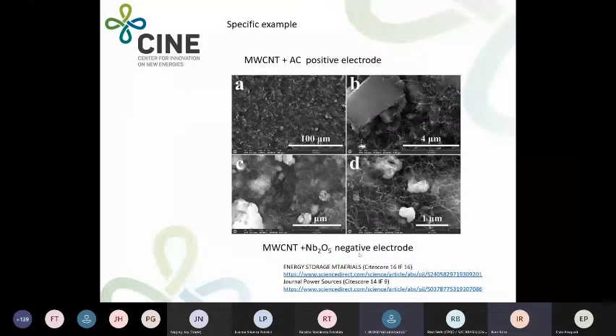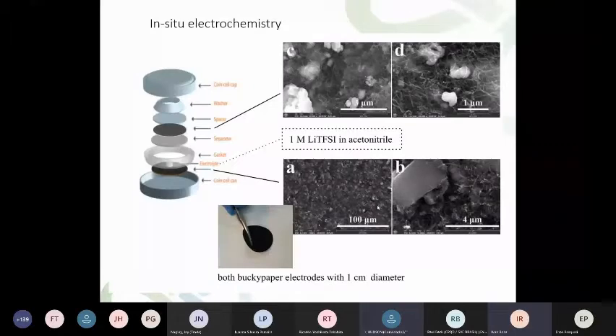So I'm going to present to you very quickly an example of what we have been doing here at Unicamp. For example, we combine here, in A and B, carbon nanotubes with activated carbon and produce a positive electrode. And then we combine here, in C and D, on the negative electrode, nanotubes with niobium pentoxide particles. We have published at least two papers in this direction using aqueous electrolytes, which are much cheaper and easier to handle, with low toxicity compared to organic electrolytes. And the data I'm going to show you today relates to organic electrolytes, which have a much wider voltage window, and we can store more energy with them.